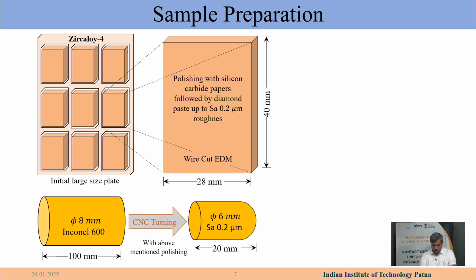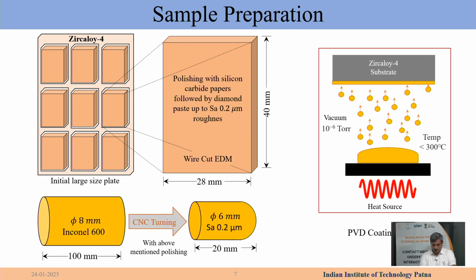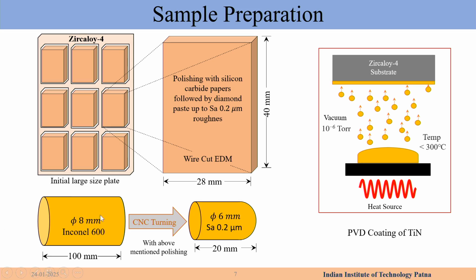So in this case now we have made these samples. This is an expensive thing, so we try to make as much as possible from what we have. We have made, for example, these 9 samples from one plate of Zircaloy. We made Inconel, turned it into 6 mm diameter, and then there was a solution to this also. At the end of this work, how can you reduce the wear? How can you reduce fretting? So we tried out titanium nitride coating. So there are 2 parts to this. One is understanding fretting, the other is a solution to reducing it.